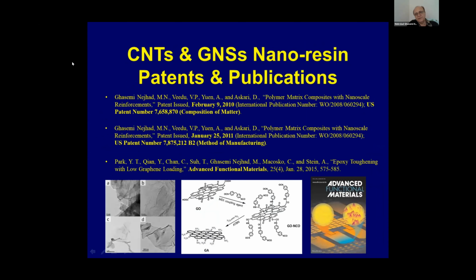So in the landmark publication we had in Advanced Functional Materials, we showed that a very small amount, up to 0.4% functionalized graphene, can improve the fracture toughness by about twice of what exists without it. So here we show the functionalized graphene that we created, shown as a TEM, and the process is given here that we started from a